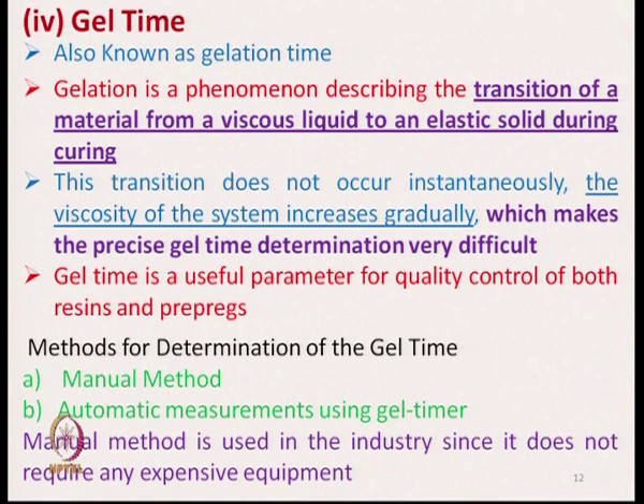The next characteristic is gel time. Gel time is normally used for the thermoset matrix. It is also known as gelation time. Gelation is a phenomenon describing the transition of a material from viscous liquid to an elastic solid during curing. So, during curing it forms an elastic solid material, and the time required from viscous liquid to elastic solid is measured. This transition does not occur instantaneously, but it takes time. The viscosity of the system increases gradually, which makes precise gel time determination very difficult.